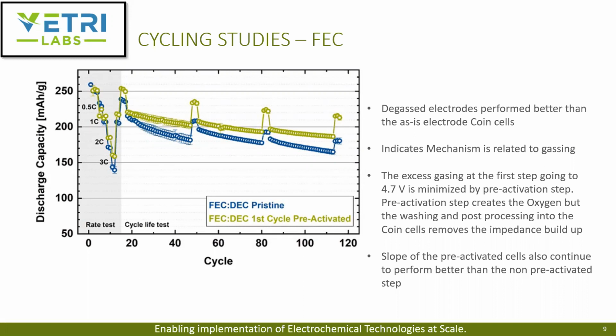I'm not sure if it's a practical approach, but this at least decouples the failure mechanism and points us toward going to higher potential. It also indicates the mechanism is related to lattice oxygen release, or gassing due to that, again due to the onset potential reaching 4.7 volts.